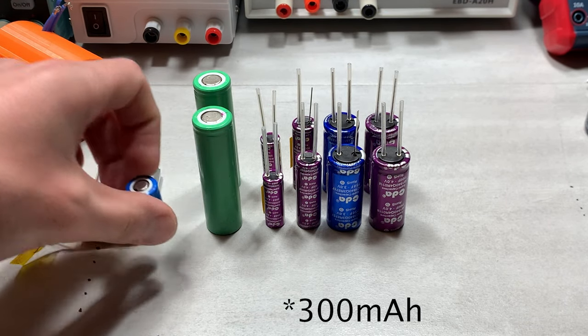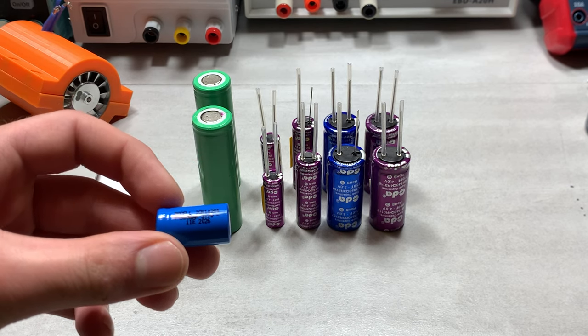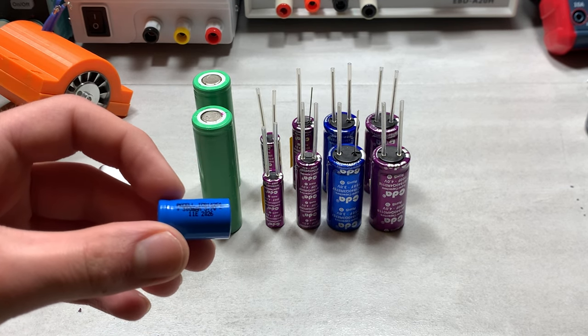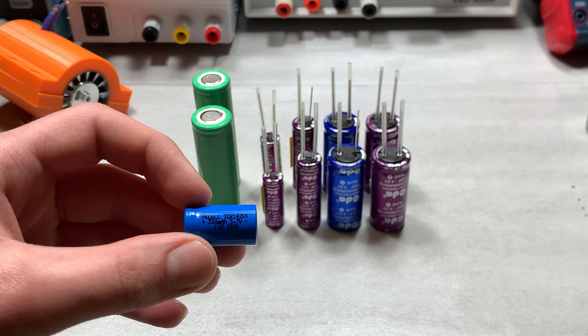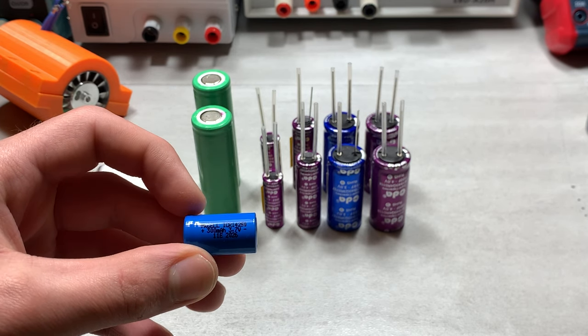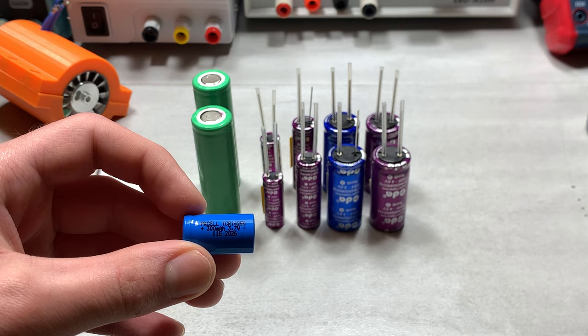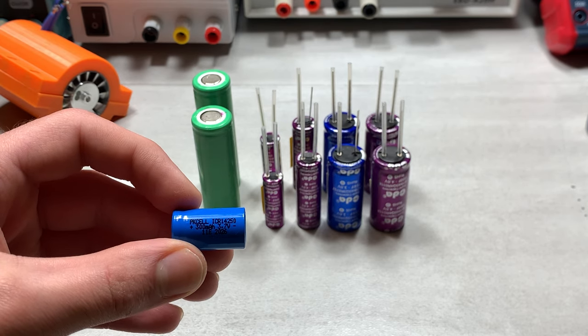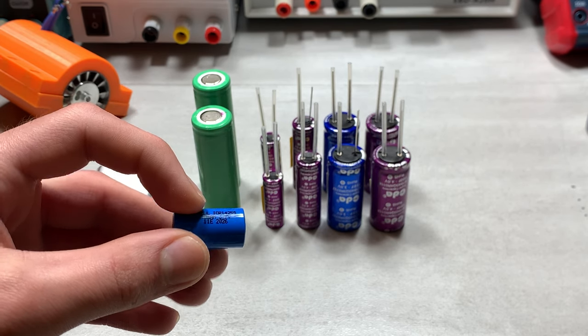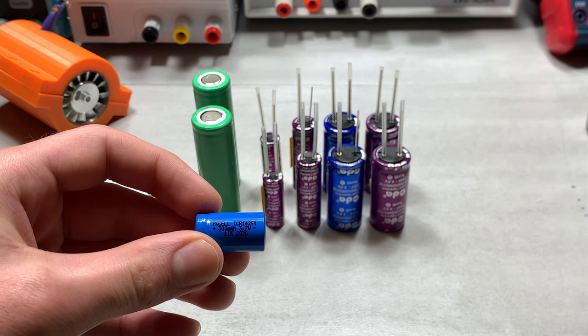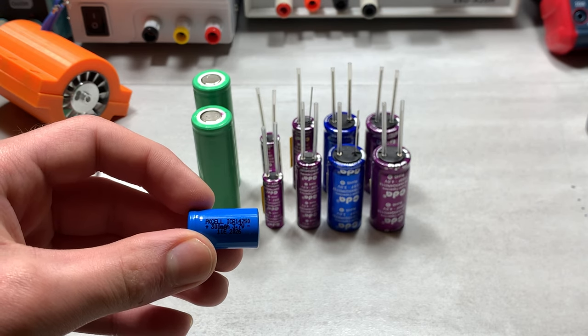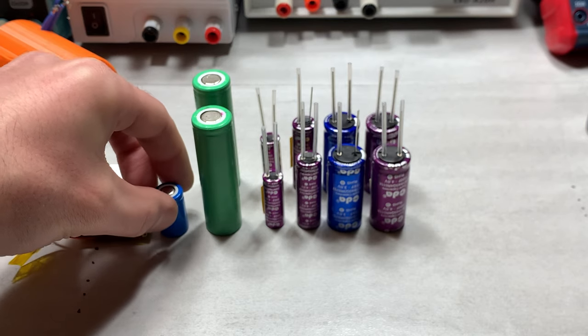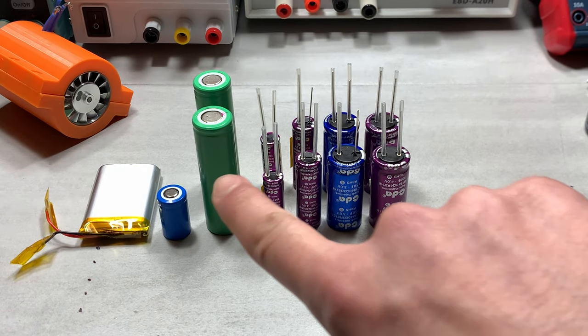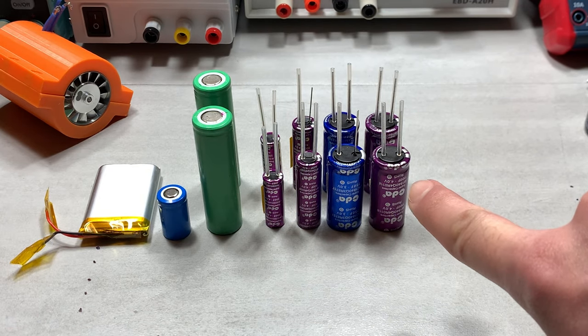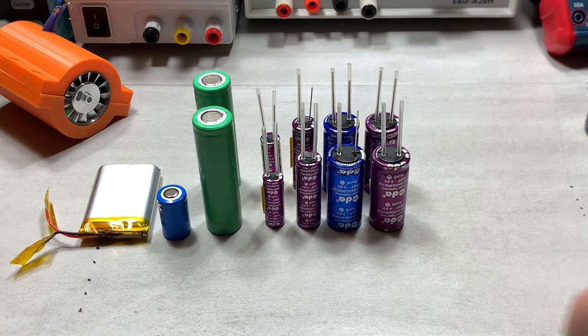And in the case of the 400 milliamp hour battery, or actually it's 300 milliamp hours. I was misremembering that. So with this 14250 300 milliamp hour battery, which is also rated for 1C, it should not be charged or discharged at more than 300 milliamps of current, or 0.3 amps. Which brings us to this monster of an energy storage solution.